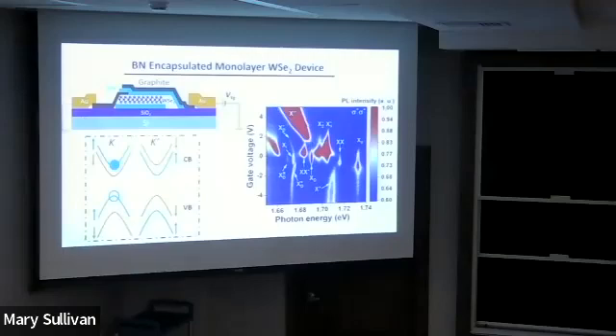So how do you actually distinguish trions from excitons here? Presumably you need more than just this photoluminescence data. Yeah, definitely. So this is exciton, that's well known, right? Trion meaning one exciton bound to a free electron or hole. So in principle, this additional Coulomb interaction will lower the energy, so emission of the photon will be at a lower energy.